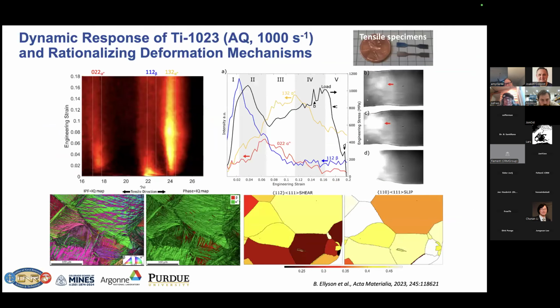In addition to Ti-6Al-4V, we've explored some metastable beta alloys as well. The nice thing is you can retain the beta phase at room temperature, and with deformation, you can promote deformation-induced phase transformation. This is like in advanced high-strength steels, for example, where you have austenite, and with deformation, you undergo transformation-induced plasticity, or TRIP, to martensite.